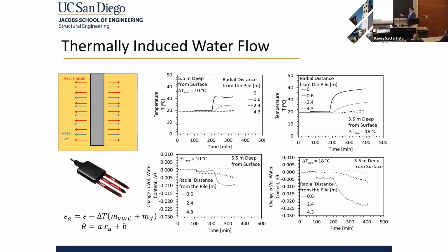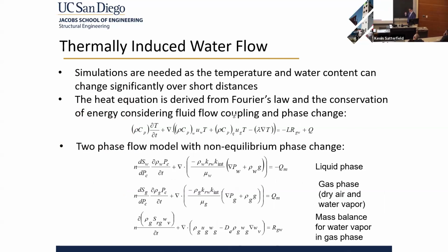These measurements are nice, but you can't have a measurement right at the pile interface, which is what we need to do a load transfer analysis. So we need to complement that with modeling. So here we used COMSOL and looked at a heat transfer model that was coupled with liquid flow, gas flow, and phase change. And this is a non-equilibrium phase change model, so it's very complicated.